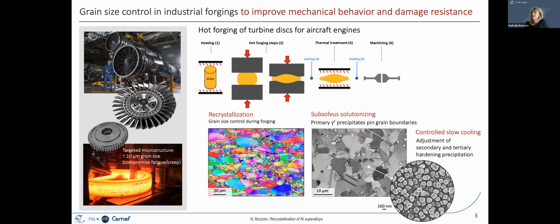For these applications, you have to achieve a targeted grain size, which allows a good compromise between the fatigue and the creep behavior. The grain size is typically 10 microns. With a typical 10 micron grain size, you achieve a good compromise between fatigue and creep solicitations. After forging operations, the material goes through a thermal treatment for dissolving partly the second phase and making it precipitate again in a controlled manner so that the mechanical behavior can be optimized. But during forging operations, these hardening precipitates are not present, so we just have to deal with the FCC matrix and second phase particles which interact with grain boundary movements.